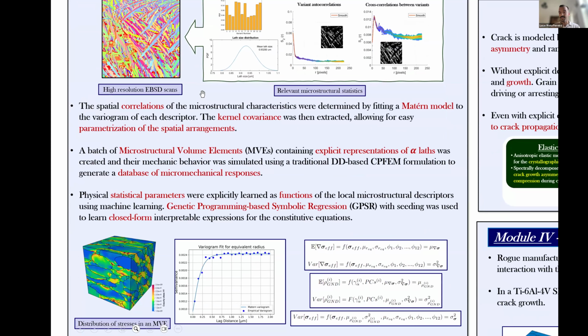To develop this model, we create a set of realizations of the joint distribution of these characteristics in which we explicitly represent the laths. We simulate these synthetic microstructures with regular crystal plasticity, and then we perform sensitivity analysis and use machine learning to figure out which of these microstructural characteristics affect which of the overall behavior of the material at this level. And then with genetic programming based symbolic regression, we come up with explicit expressions of these parameters, such that we can now represent the microstructure in a crystal plasticity formulation without explicitly representing the morphology of the grains.